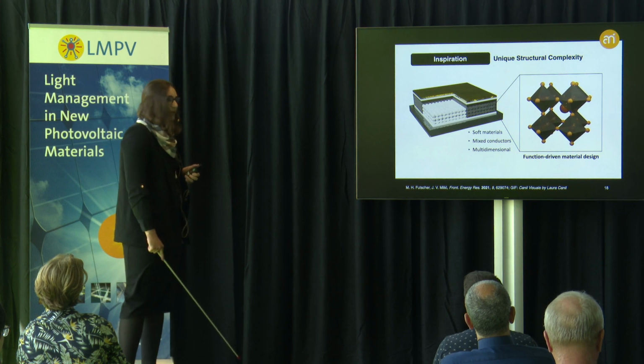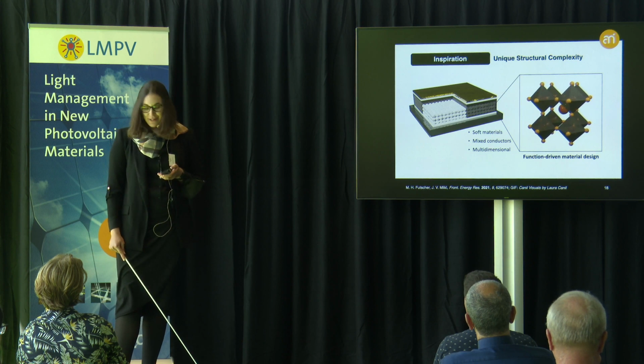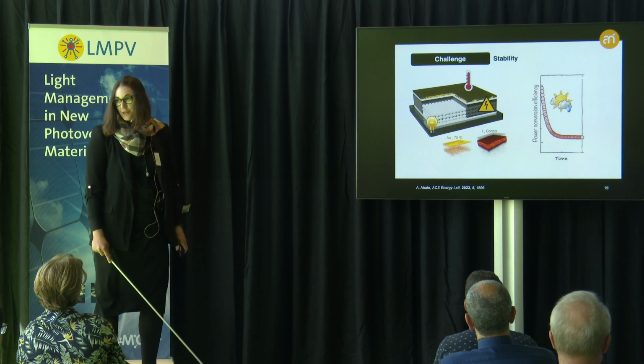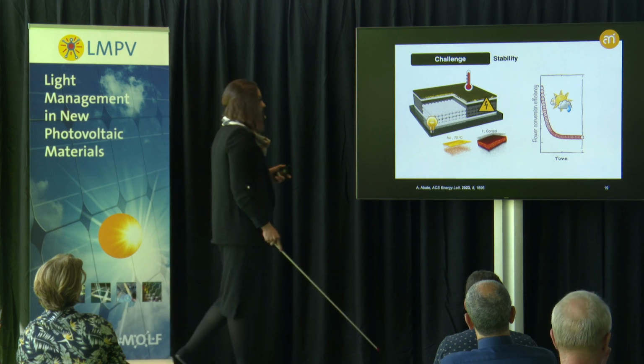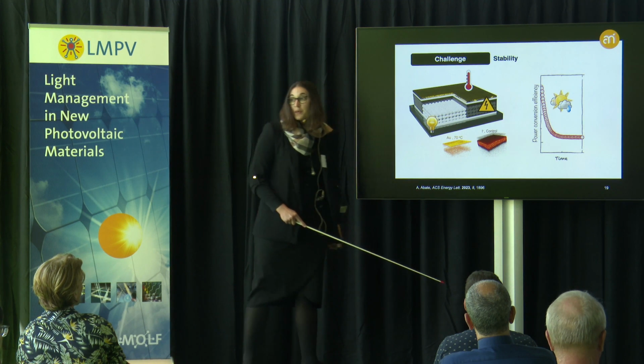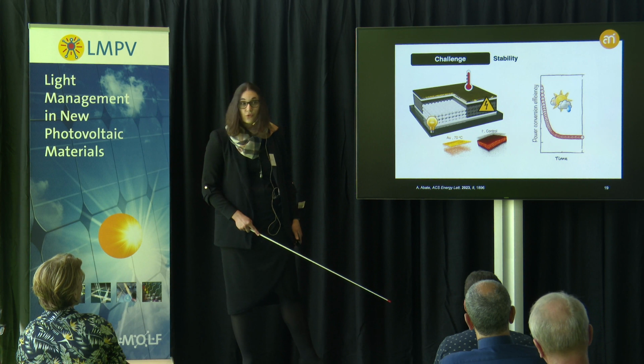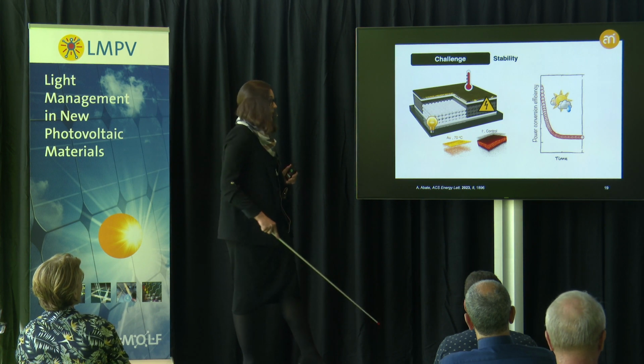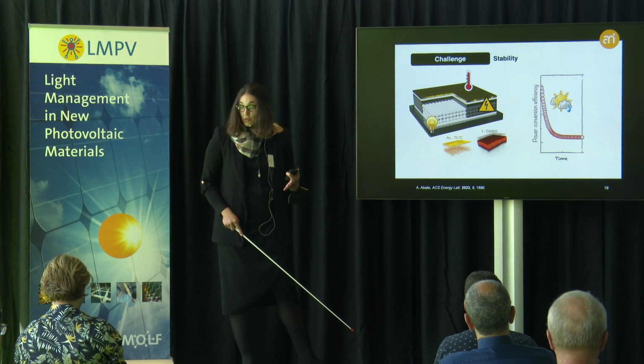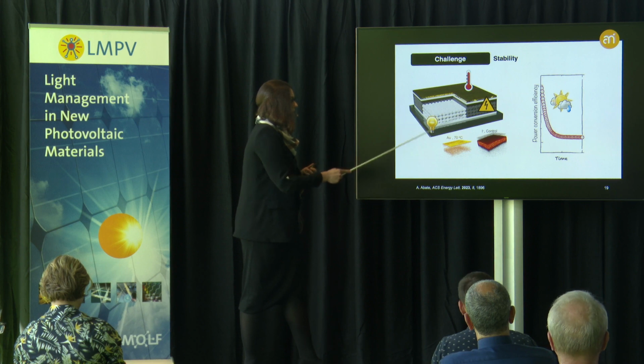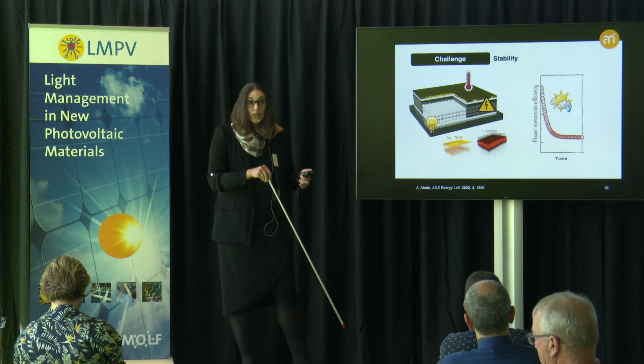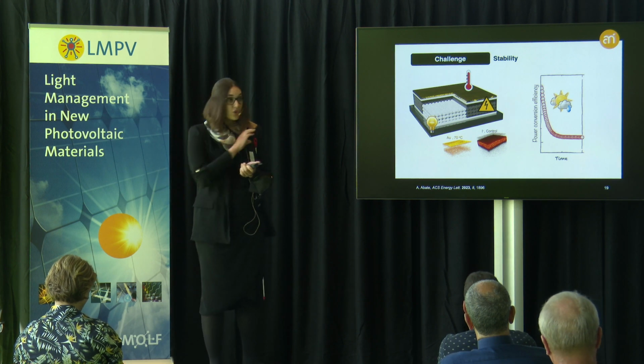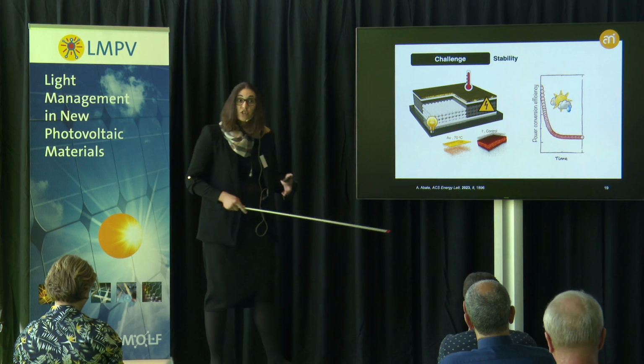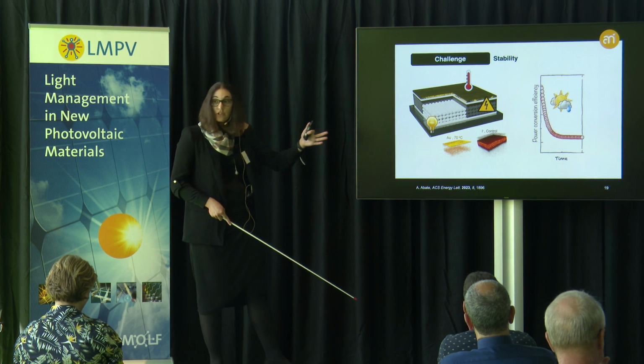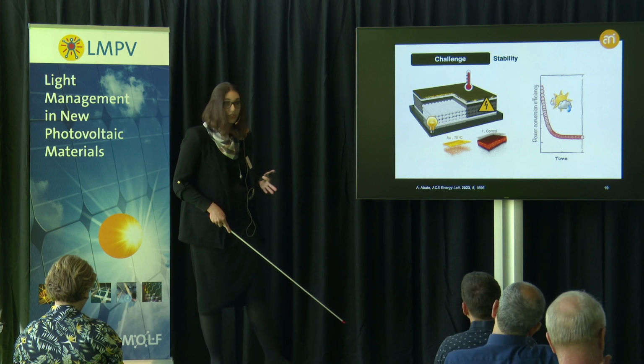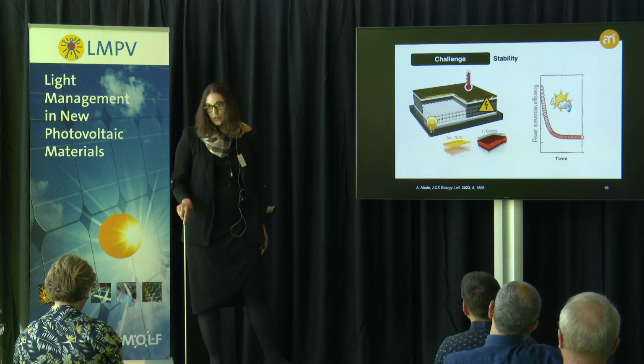also associated with one of their major challenges that we are all painfully aware of, which is in fact their limited stability, leading to their performances across these different functionalities and device architectures to gradually decrease over time, especially when they're exposed to external environmental factors in the form of oxygen or moisture due to the reactivity to these factors, but also as a result of these internal ion migrations within the hybrid perovskite layer that is here schematically represented inside these typical photovoltaic devices when they're sandwiched between different selective charge extraction layers, but also across these layers that is actually accelerated under the operating conditions of temperature changes, voltage bias, or light, leading to a number of degradation processes that pose one of the main challenges in this research domain.